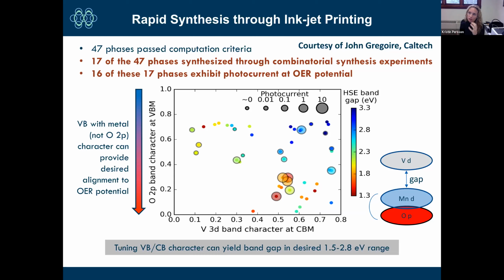And that really did correlate also with what kind of states we were able to see at the conduction band minimum and the valence band maximum. So having a high amount of vanadium 3d states at the conduction band minimum was a good thing, because then you're basically lowering to get a tighter band gap, and having a low amount of oxygen 2p states, which tend to correlate with low mobility. So you want to avoid those as much as possible at the valence band maximum. Those two design metrics helped us to go forward and screen for more materials that were more promising as well.